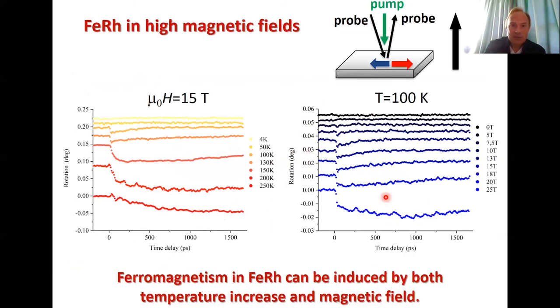So that's what we performed. First we measured magneto-optical Kerr effects, not THz emission anymore, only Kerr effects. We are at the moment not that rich in the choice of experimental techniques there. It's magneto-optical Kerr effects and maybe Faraday effects. So we applied a magnetic field perpendicular to the sample and measured Kerr rotation upon reflection from the sample.